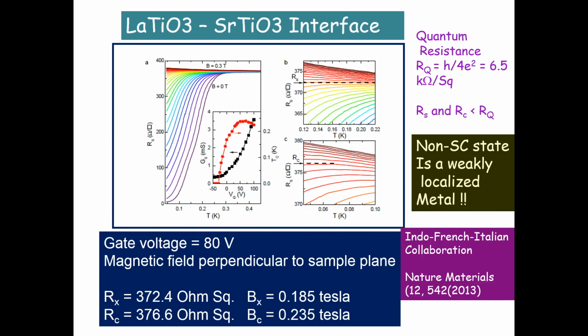So this is the field-driven superconductor-normal transition in LTO-STO. Field is applied perpendicular to the plane of the 2D electron gas, and you see here sheet resistance as a function of temperature at different values of magnetic field going up like that. And you see the conductance goes up as I increase the gate voltage, and the transition temperature goes up as I increase the gate voltage.